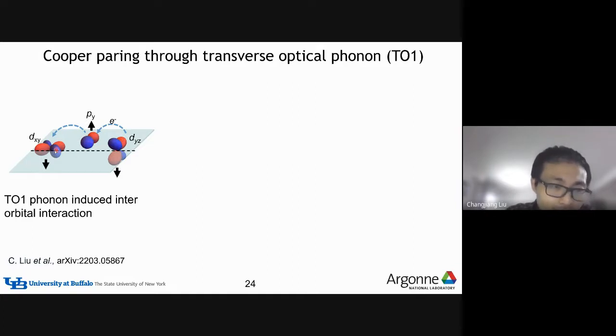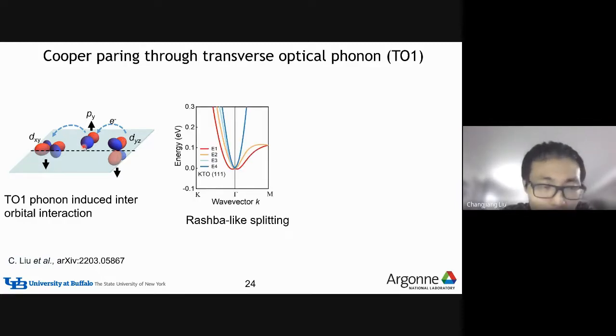Suppose here you have the dxy, the py and the dyz orbitals, and in the ideal case, when there is no phonon, they are in a straight line. So these orbitals are orthogonal to each other, which means the hopping is prohibited. Now, when you have a transverse optical mode phonon, these are no longer at the center. So mathematically they are no longer orthogonal to each other. So there will be a hopping between these two orbitals and eventually to this d orbital. So basically this transverse phonon can induce a hopping between different d orbitals, which would otherwise be inhibited by the orthogonality of the orbitals, right?